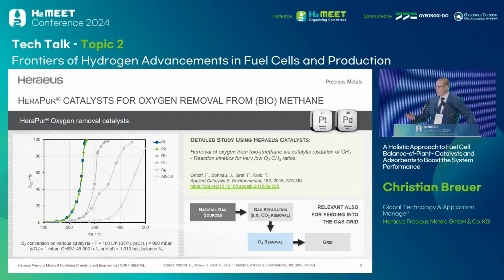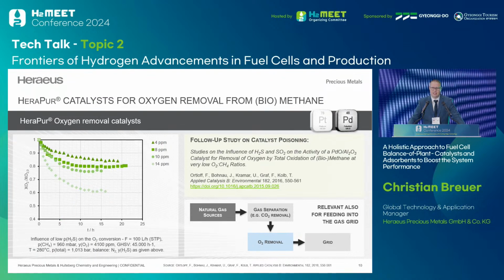And then there's a nice study that's not been done by us, but by a university in Karlsruhe. They had been using some catalysts we provided, which really nicely shows you the activity profiles of the catalyst, and especially nice the use of platinum and palladium. What I really like about this study is they didn't just stop there, but they also studied the sulfur deactivation of these catalysts, which of course, if you look at biogas for example, is always something you have to be aware of. And they could very much show that depending on the degree of sulfur, the concentration of sulfur in, you end up with different deactivated states.